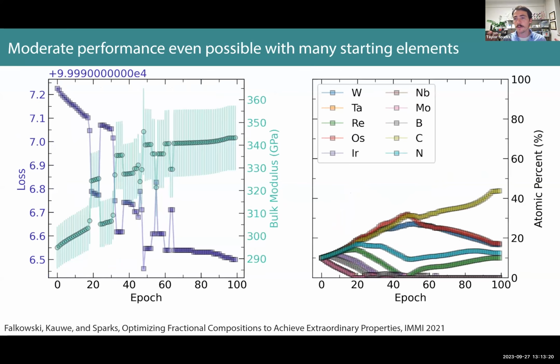We then tried to break it. We said, let's give it several different components or objectives to try and reach, while also giving it 10 different elements. And yeah, it did kind of break it, but I was surprised how semi-reasonable it was. For example, when we gave it 10 different elements, it turned off half of them. It quickly turned off a bunch because, again, the training data that this was trained off of was a bunch of DFT calculated materials where 10 elements are not present in that data set. And so it's learned that it should tend to have smaller mixtures of materials.